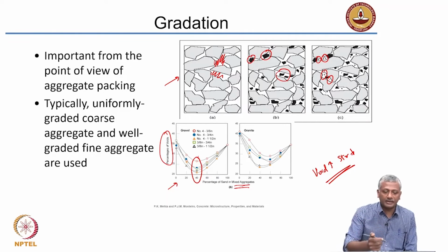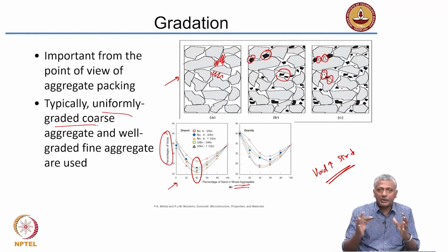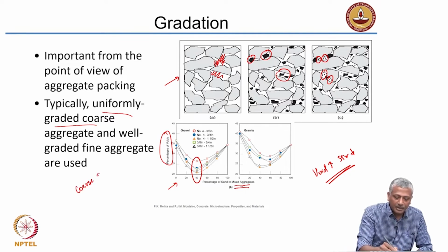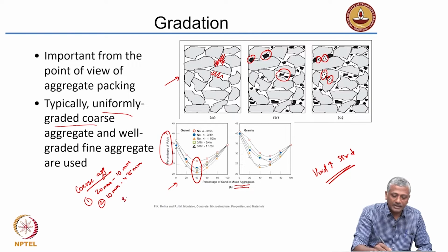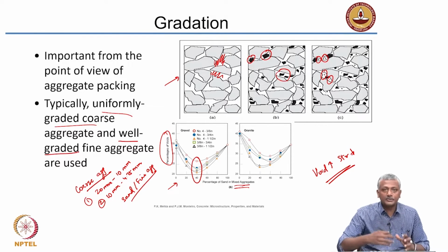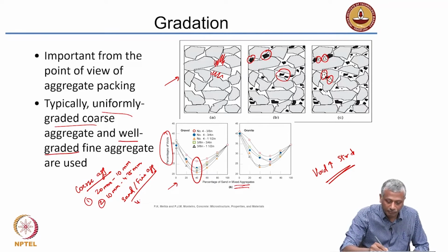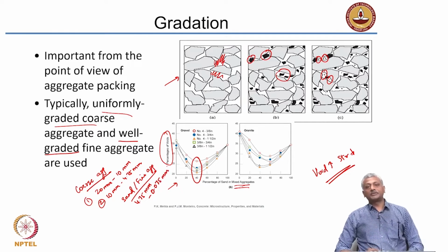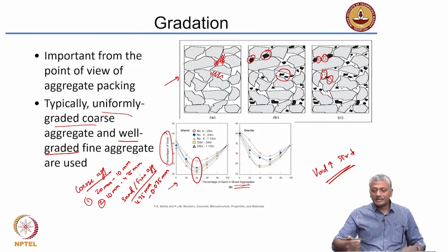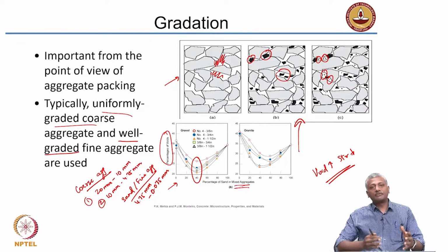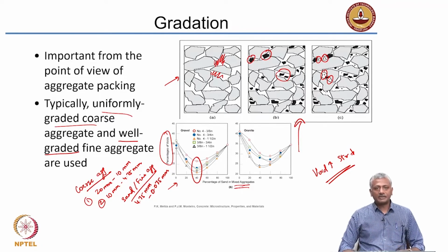Generally, what happens is when you get the coarse aggregate, it is uniformly graded. That means it will have a narrow range of particle sizes. So, coarse aggregates typically used in concrete are first 20 mm to 10 mm, and the second size is typically 10 mm to 4.75 mm. Sand, or fine aggregate, on the other hand, is well graded. That means it has particles in a large range. It goes all the way from 4.75 millimeters to 75 microns or 0.075 millimeter. So, particle sizes vary over a large range, because of which they can start filling up the voids left behind by the previous set of aggregates.